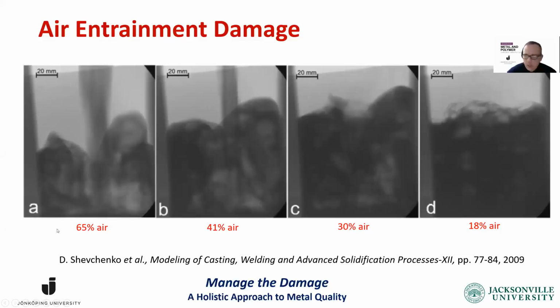And here's another research that I came across, again from air liquid aluminum mixture created by pouring from one bucket to the other. Here at the beginning, we have 65% air, only 35% liquid aluminum. And with time, it goes up to about 18%, but that's still a lot of air, a lot of damage that's created just because we treat liquid aluminum as if it were water.